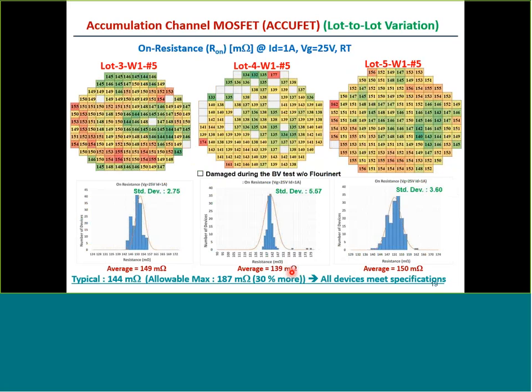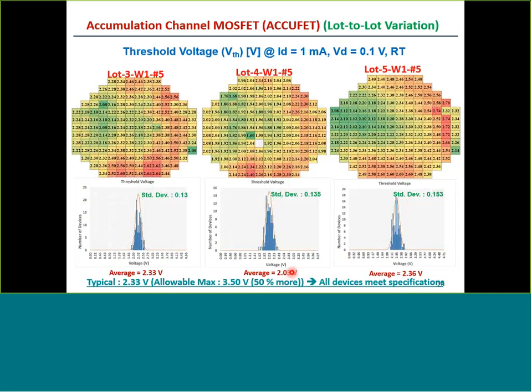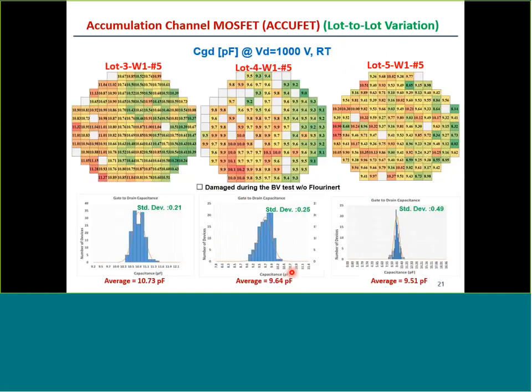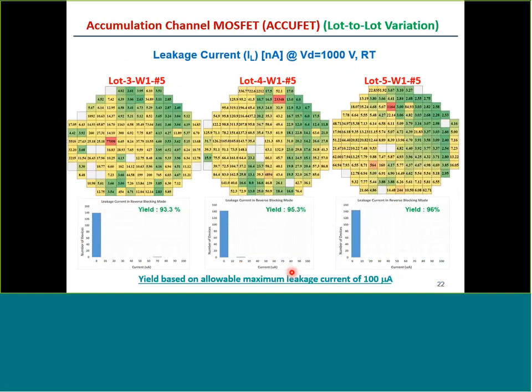Turning to lot variations, you can see here 3 wafers from 3 different lots, and you can see again the average values are given on the screen, and they fall in a pretty tight distribution. Our threshold voltages are also very uniform from lot to lot. And the CGD values are also very uniform from lot to lot. Finally, if you look at the leakage currents, they all remain in the nanoamp range among all the devices. So as a consequence, the yields tend to be in the 90% plus